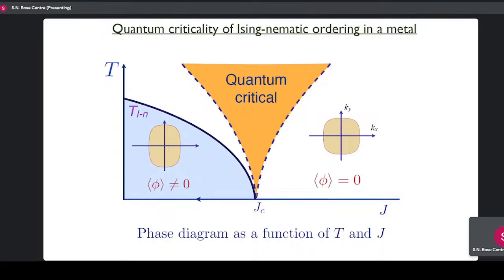But the focus of this talk will be in this so-called quantum critical region, where you're studying the physics of the zero temperature quantum critical point. All right, so what do we know about such phase transitions? First of all, if you take the finite temperature phase transition, that's just an Ising symmetry of a quantum system, but nevertheless at finite temperature. And what we know is that, in fact, the usual Ising model, which I think was discussed yesterday too, solved by Onsager, the universality class would be exactly the same. Even though this is a much more complicated system, the Ising criticality doesn't change anything, and it's just a two-dimensional Ising transition.